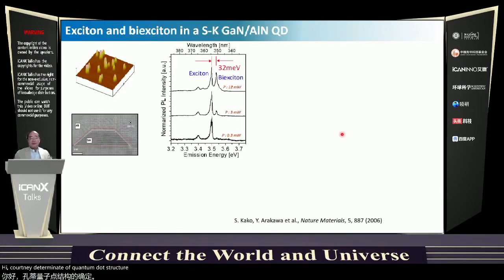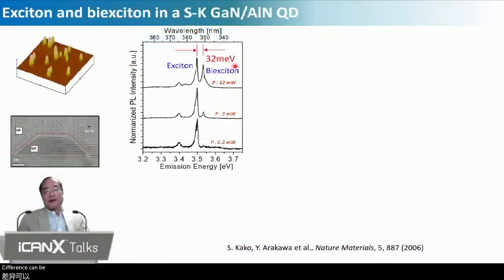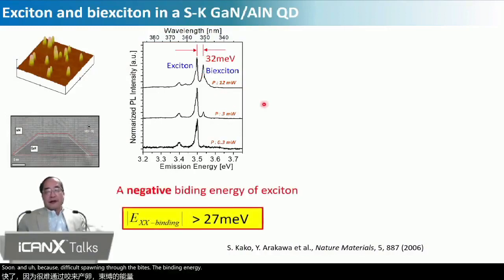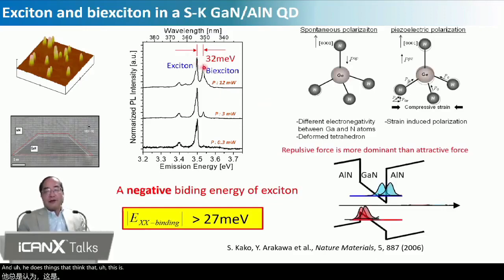So we try to use gallium nitride based quantum dot structures, growing high quality gallium nitride quantum dot structures by ourselves. Indeed, already 15 years ago, we had very high quality gallium nitride quantum dot structures on aluminum nitride. And we observed the spectrum of the bi-exciton and the exciton, and a 32 millielectron volt difference can be seen, corresponding to the bi-exciton binding energy. And the interesting thing is that this bi-exciton peak is located at the higher energy side of the exciton. So we should say that this is a negative binding energy of the bi-exciton.